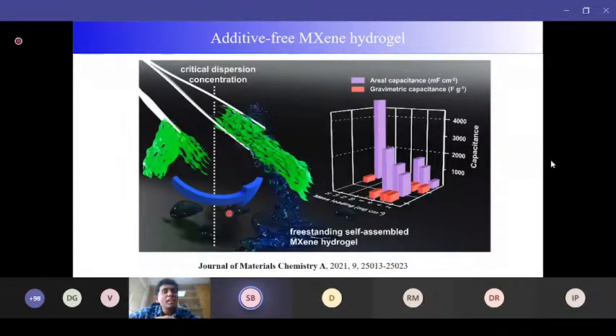And next, we targeted the following. In the previous case, we made the MXene hydrogel, but we needed the graphene to make the gel, because our previous effort to make a freestanding MXene hydrogel went in vain, so we inspected why we are not getting the freestanding MXene hydrogel, why we need the graphene.